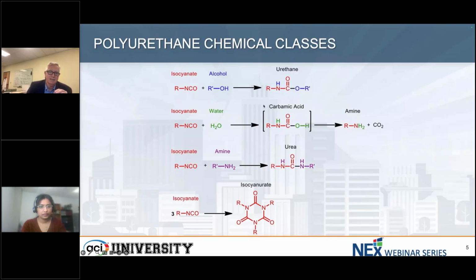You can also have materials that are one part polyurethanes, where basically you've made a polyol, but you haven't cross-linked it yet. What's going to happen there is that the isocyanate is going to react with water. It's going to form the amine. The amine is going to react with isocyanate and form a urea. So in that, you're absorbing water from the environment to cross-link it with a polyurea. And that's a one-part polyurethane. You see that a lot in coatings, and it's very moisture and temperature dependent.